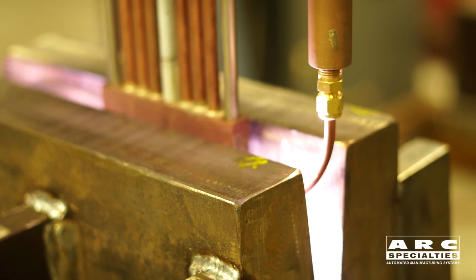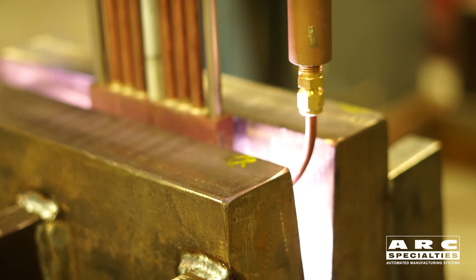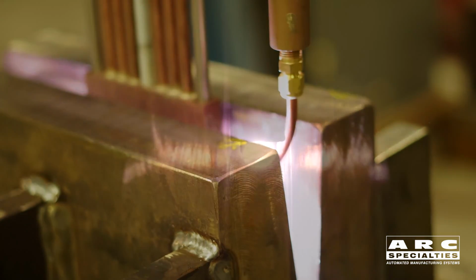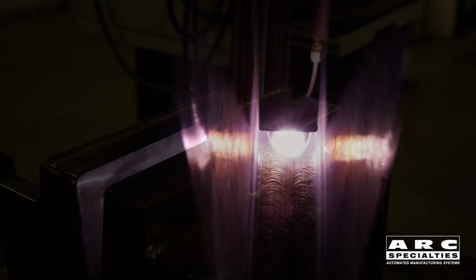So what we've done is we've added hot wire. Hot wire is a technique we use to improve deposition rate and reduce dilution when we're gas tungsten arc welding. We're using our own power supply because it's AC and it's constant voltage. We like these features because with constant voltage, it automatically corrects for variation in wire speed and stickout. We like AC because of the electromagnetic interference between the hot wire power supply and the DC arc of the gas tungsten arc torch. We're actually causing the arc to oscillate at a frequency of 60 Hz.